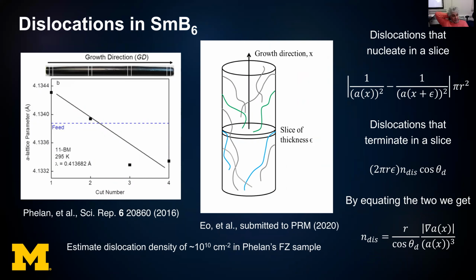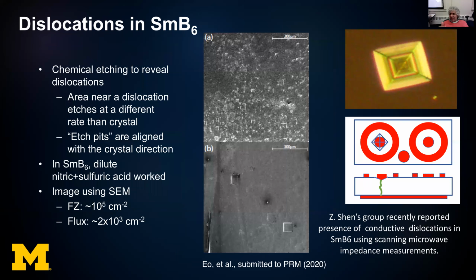For example, in this particular floating zone sample, there is a known variation of the lattice constant, and we could relate the gradient of the lattice constant variation to the density of dislocations. Our original estimates are on the order of 10 to the 10 dislocations per square centimeter for floating zone samples. And we have found the presence of dislocations using etching techniques. When you do an etching, if you have the right etchant, you might get something called etch pit dislocations. These are sort of lower bounds for the dislocations, and indeed the floating zone samples, at least in this study, show much higher concentration than the flux-grown samples. We believe these are not the true dislocation densities, but they must be present.